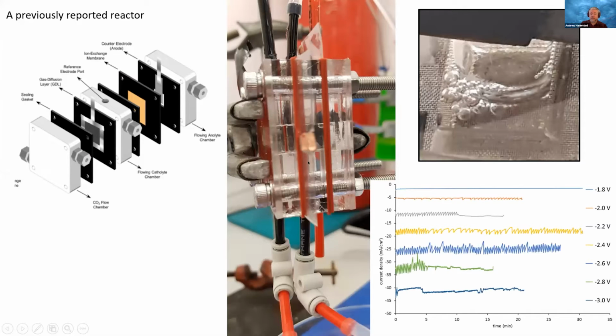We essentially replicated this out of Perspex. This gave us the benefit of being able to very easily see what's going on inside the cell in terms of any bubble formation. And what we did see was that, yes, there were a lot of bubbles and that they generated a lot of noise in the electrical response. We also saw, as you can see from the top image here, that those bubbles tended to often pool, and when they pooled, you lost active electrode area and the performance dropped off.